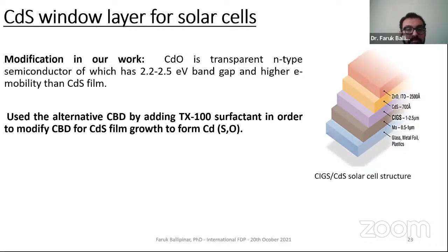So CBD is the common technique for the CdS. Even some industries in CIGS and cadmium telluride use the chemical bath deposition technique for commercialized solar panel technologies. So we use the same technique. The only modification and challenging part in this project is adding TX100 surfactant. So we created an alternative chemical bath deposition to form an oxysulfide material, cadmium oxysulfide. Basically, we modified the conventional technique by adding TX100 surfactant.